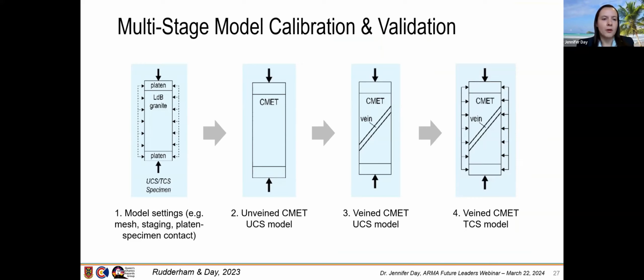The multi-stage model calibration and validation first involved using well-published and well-understood LdB granite to simulate the UCS and TCS tests. This rock type was used to calibrate the model settings, so the mesh, staging, and platen specimen contact properties. Then using that model setup, Giselle simulated unveined UCS models of the CMET, and then used the lab test data to calibrate that. Then she added the vein to that model, and also used published TCS data to validate the model for the veined cement sample.